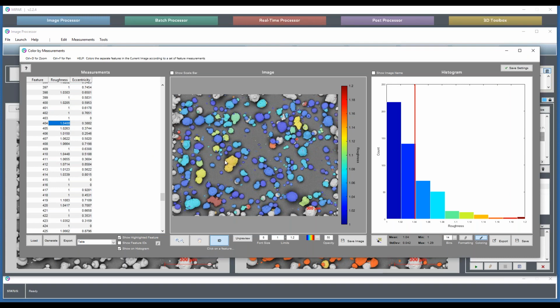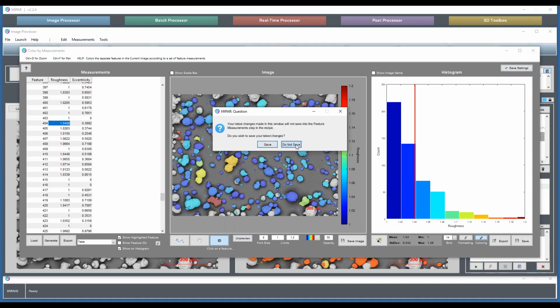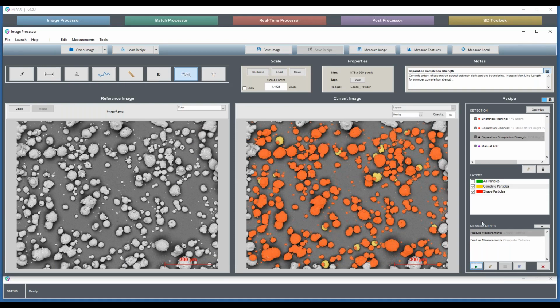And with size, I want to mention that the client did not set out expecting to use image analysis for particle sizing. They had a laser-based spectroscopy approach where they would pass a powder sample through a laser, they would get diffraction from the laser, and they would then have a plot of what the expected histogram of particle size was. They weren't able to see the particles, as you know, with that sort of method. They just flow a bunch through the laser setup and they get a plot. And what they came to realize was that their plot was wrong. They were missing a lot of fine particles in that plot because those fine particles were stuck to bigger ones and were getting counted as one.